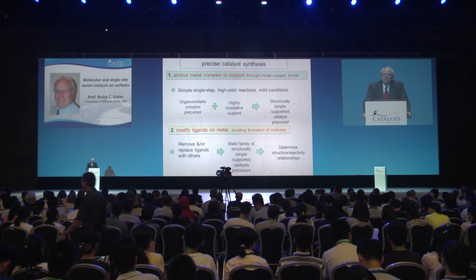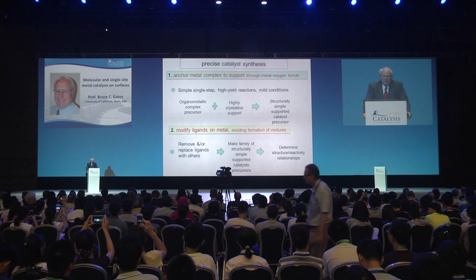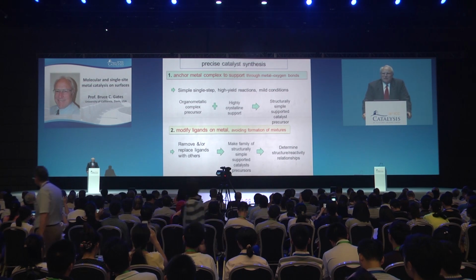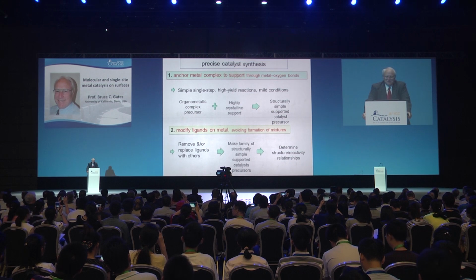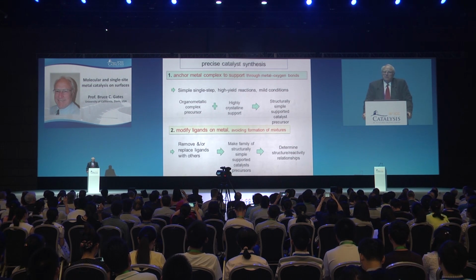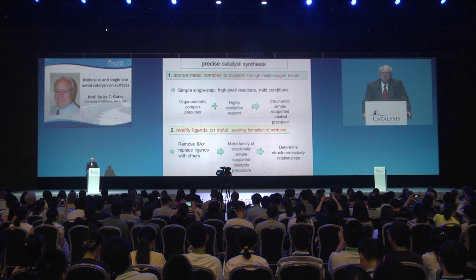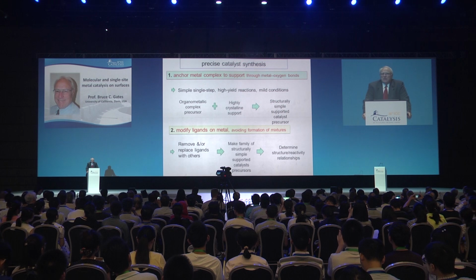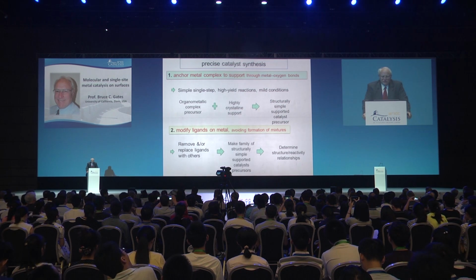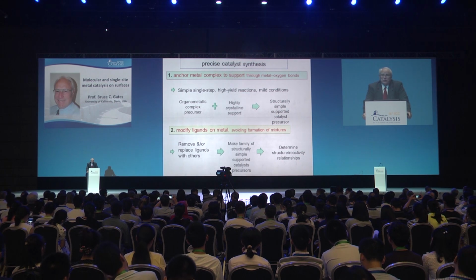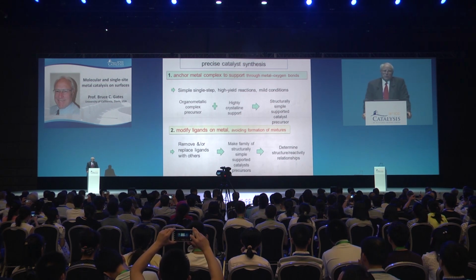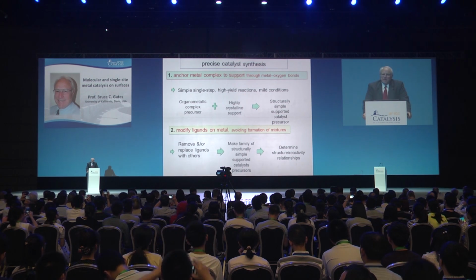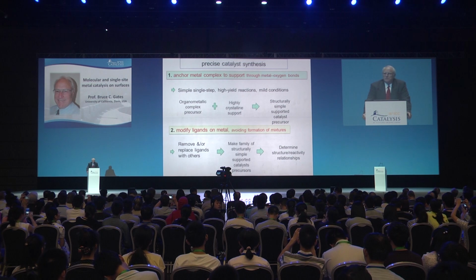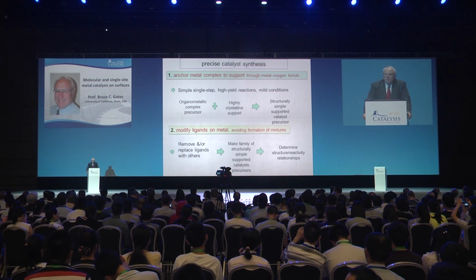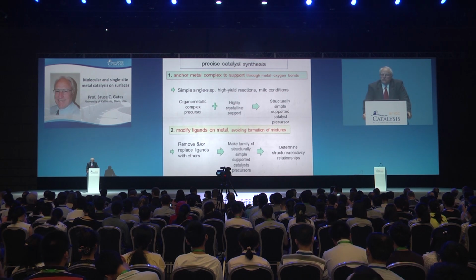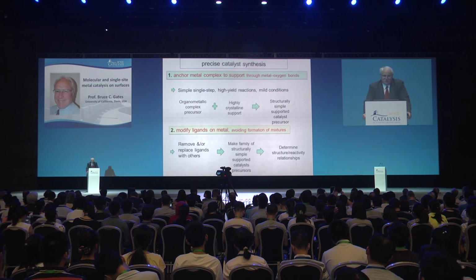So how could one approach precise synthesis? Here's a kind of guideline, simplistic perhaps. Take a reactive metal-containing precursor—it won't be a metal salt, it'll be an organometallic compound. Let it react with sites on the surface of a support that's highly uniform, crystalline, presenting a nearly uniform array of sites for bonding, thereby making a structure bonded to the support that's analogous to a molecule. Then work on that: remove ligands, change ligands, replace ligands, let ligands react.